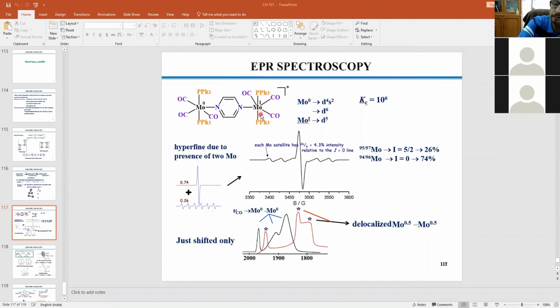And in that case, we will have 6 lines only, 3 lines here, 3 lines here, and the central line. But experimentally, we are getting 11 lines. So what would be the origin of the 11 lines? That means this unpaired electron is essentially facing both the moly nuclei. And that is only possible if this electron shuttles like this, the unpaired electron I'm talking about. And if that is possible, then the electronic forms would be at the mixed valence state, moly 0.5, moly 0.5, instead of moly 0, moly 1. So this would be the definition.